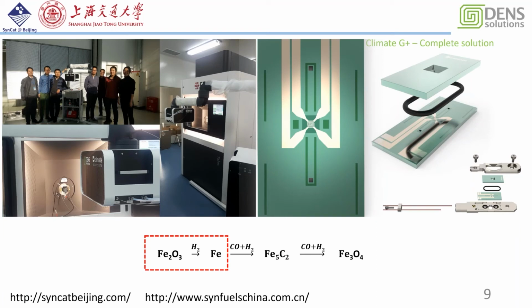This reaction looks very simple, but by doing this reaction, we found a very complicated chemical view. And this information can only be explained by macrokinetics, not thermodynamics. This complicated behavior also helps us understand a lot of the fundamental science behind it. And this story is not so successful because we have to use extremely critical conditions to get the iron, so this condition is not so favorable for industrial processes. But finally, we got some good information, and I hope it can raise your interest in understanding the chemical reactions related to the reduction of metal oxides.